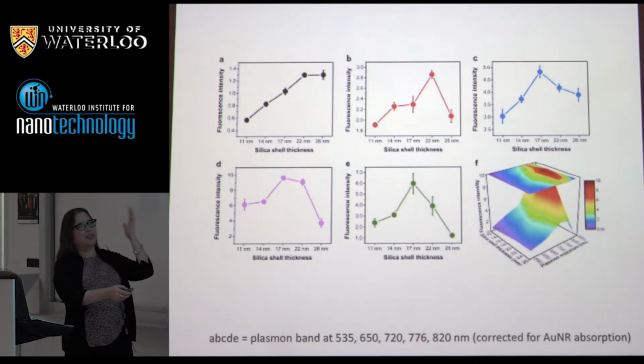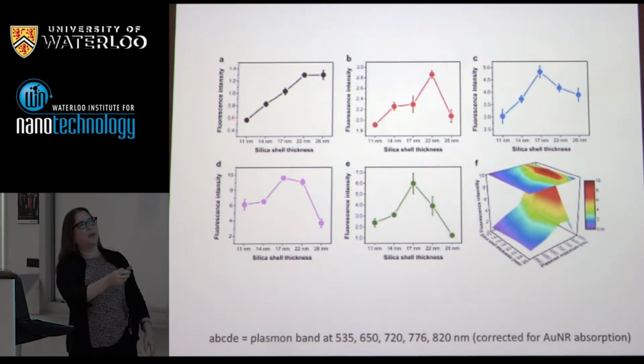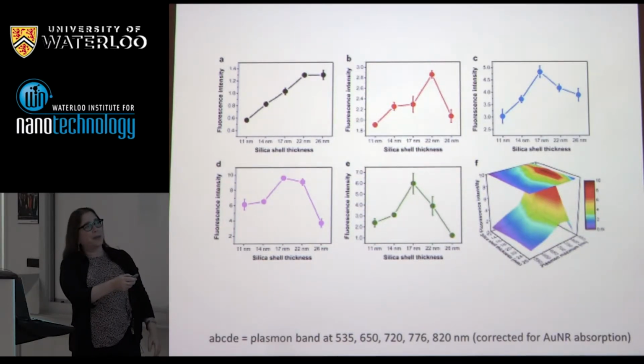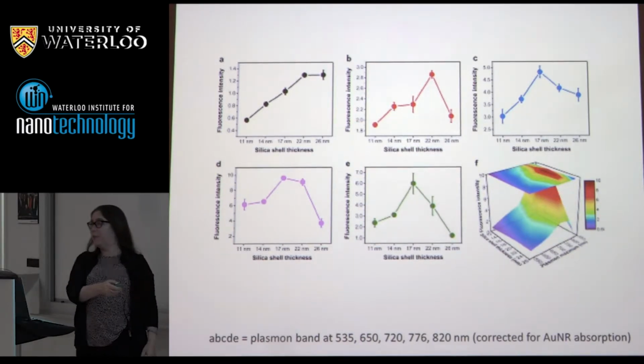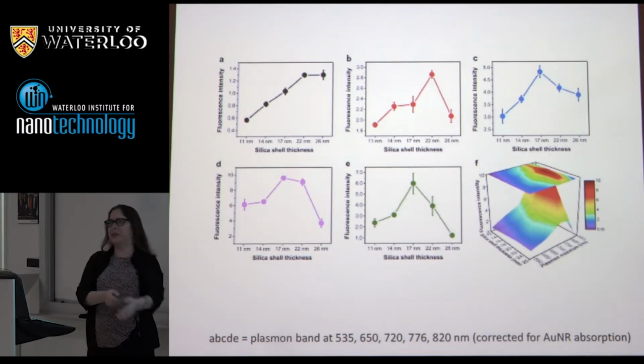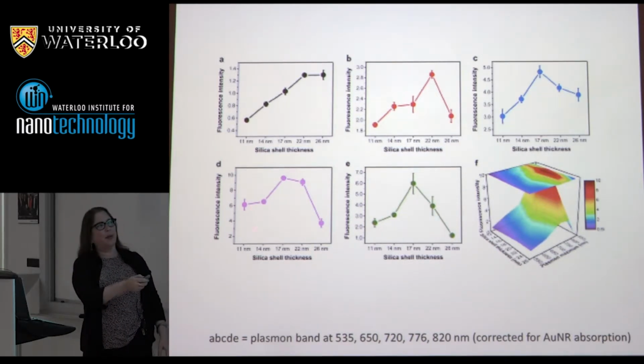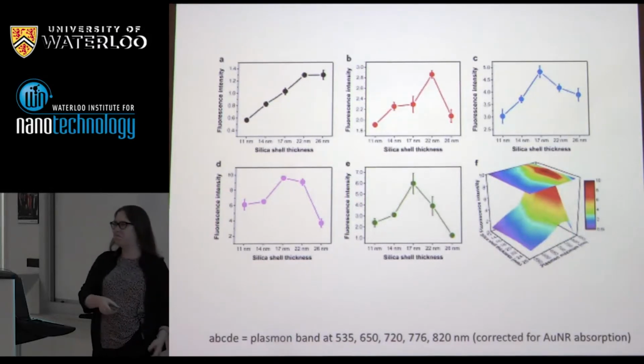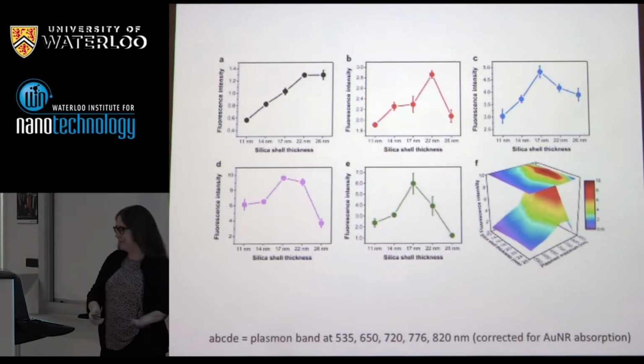And I just want to point your attention to the hot spot. Okay, where do we get the most light out of this dye, if that's all we cared about? Well, we want to be where the plasmons are right on top of the absorption and emission. You want to be right on top. That makes some sense. And then where do you want to be? You want to be about 17 nanometers out. And how much more light do you get out compared to the free dye at that same concentration, all that stuff? It's about a factor of 9. Okay, so now we know.